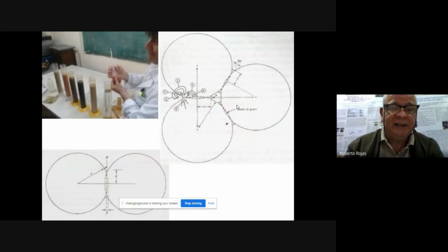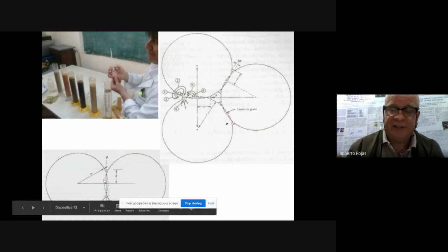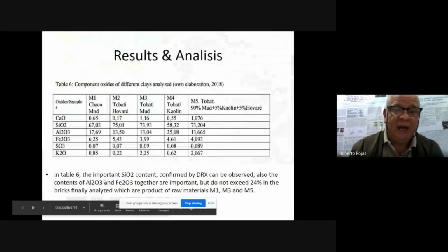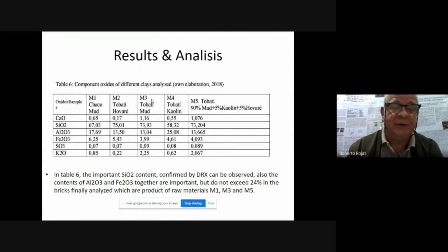Here are the tests of Poyocos, and the theory was this one before. This was the mechanism of adhesion known before this research. Here we have the Chaco mud. One of the bricks was made of this. The other was M3, Tobatí mud. And the other, the fifth one, was a mixture of 3, 2, and 4 in this order: 90% mud, 5% kaolin, and 5% Hovaré.